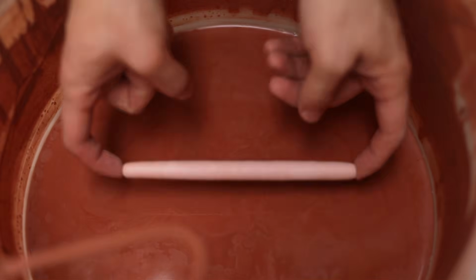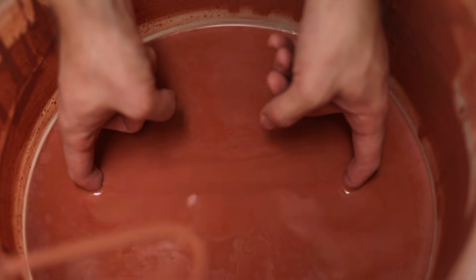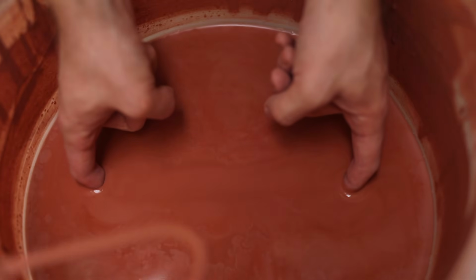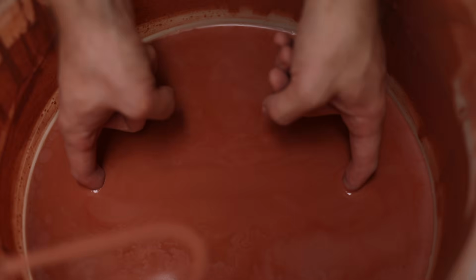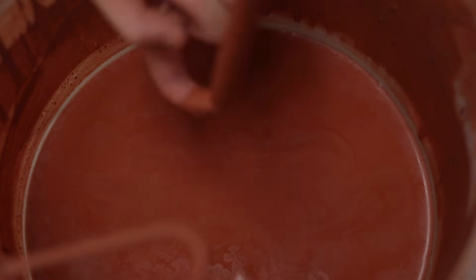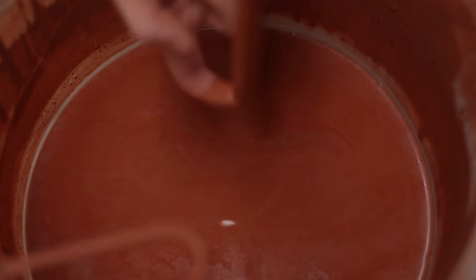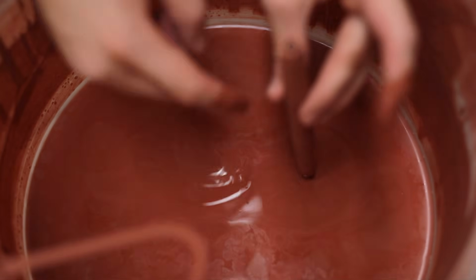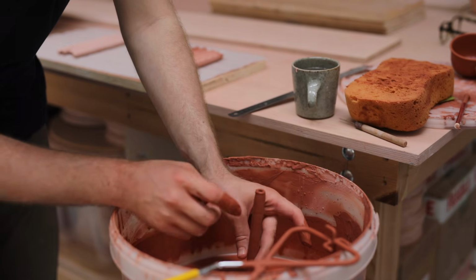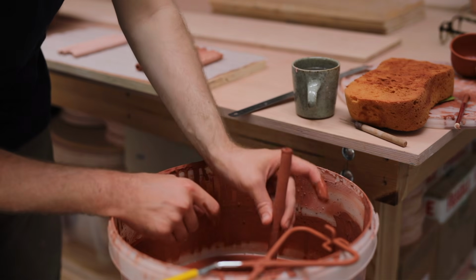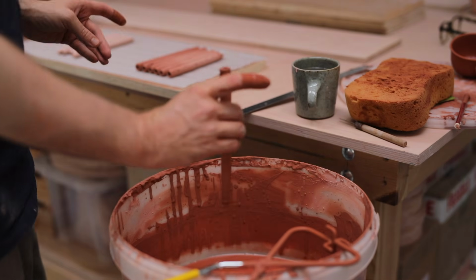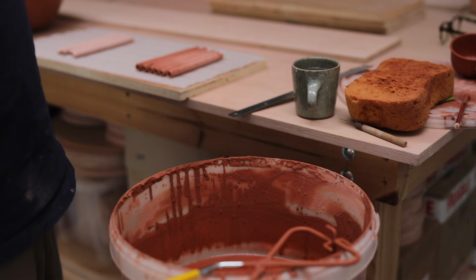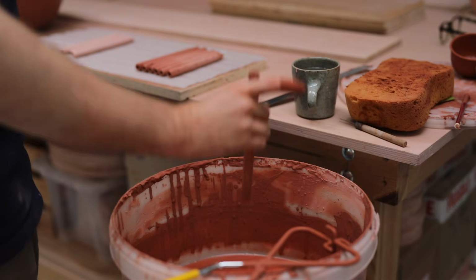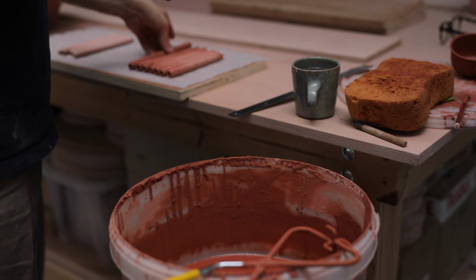The glazing of these is quite straightforward. I make sure that none of it goes inside the hollow, otherwise it can be a pain to clean out properly. But what's worse, if you aren't able to clean all of that glaze up, there's a chance it'll stick during the firing to the metal rod it's inserted on. But once these have been allowed to fully dry out for a day or so, I'll go over each one, double check them, and I'll clean over the glazed surface to make it as smooth and even as it can possibly be.